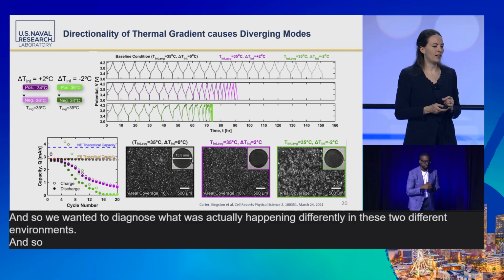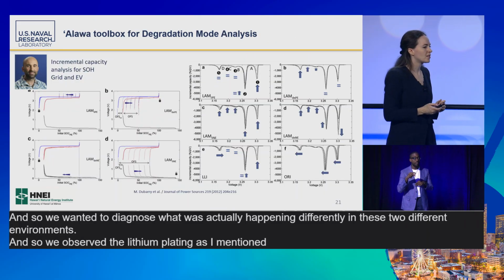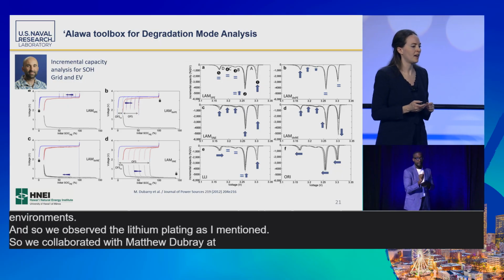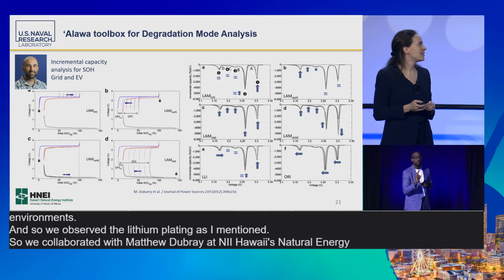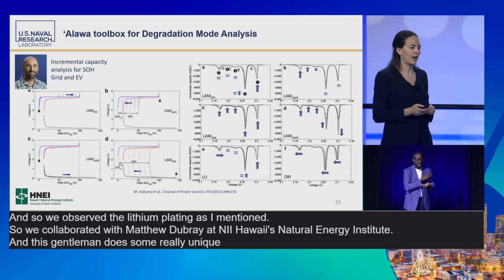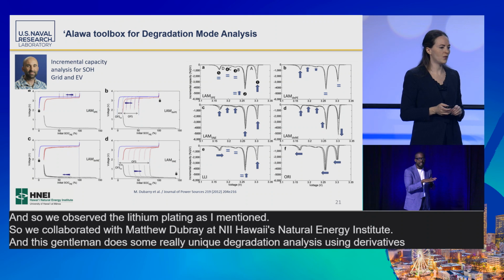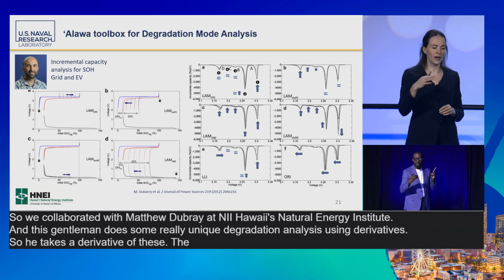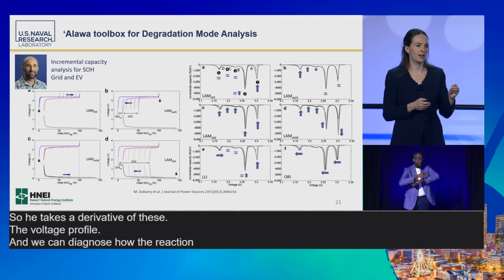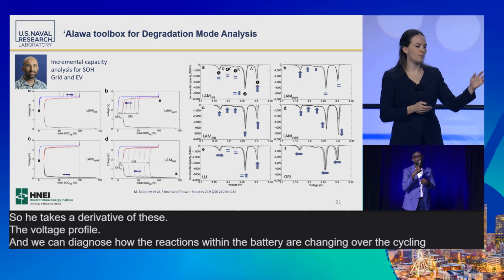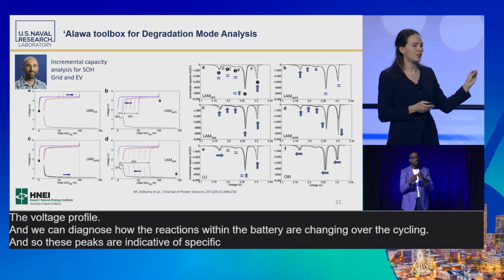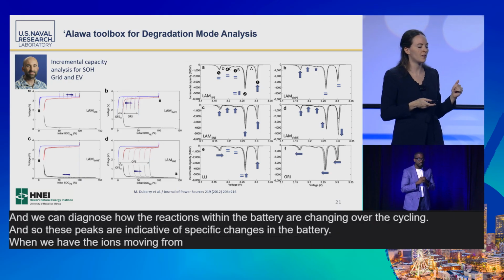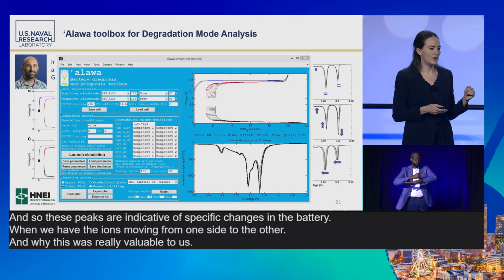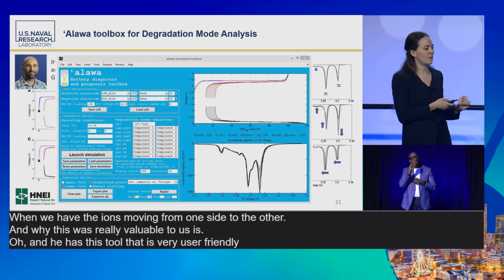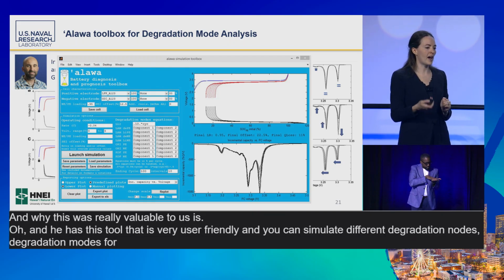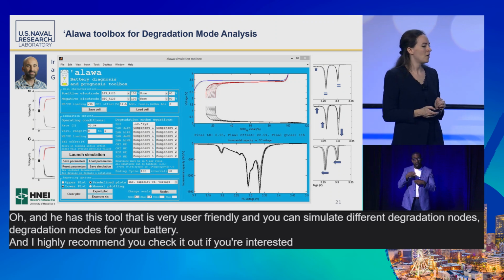We observed the lithium plating, as I mentioned. So we collaborated with Matthew Dubray at HNEI, Hawaii's Natural Energy Institute. This gentleman does some really unique degradation analysis using derivatives. He takes the derivative of the voltage profile, and we can diagnose how the reactions within the battery are changing over the cycling. These peaks are indicative of specific changes in the battery when we have the ions moving from one side to the other. Why this was really valuable to us is that he has a very user-friendly tool where you can simulate different degradation modes for your battery, and I highly recommend you check it out if you're interested in battery research.